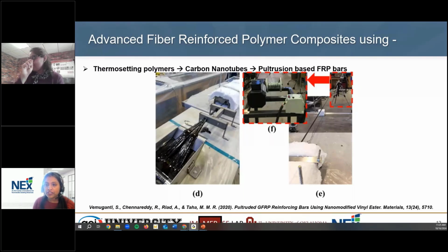With moving forward with our next question, what improvements in 3D printing technology can improve this design? Okay, that's also a great question. So, as I proposed in some of the recommendations for future work, right now with the thermogravimetric analysis, we're seeing that the fiber filament itself, which is supposed to actually be 100% fiber, has to be melted down and therefore it has 50% thermoplastic. If that 50% fiber is increased to about 65%, like a rebar with about 66% fiber volume fraction, you're already seeing more fiber in there. More fiber means more stiffness, more strength. So that improvement is primary, according to me, in terms of the materials aspect.